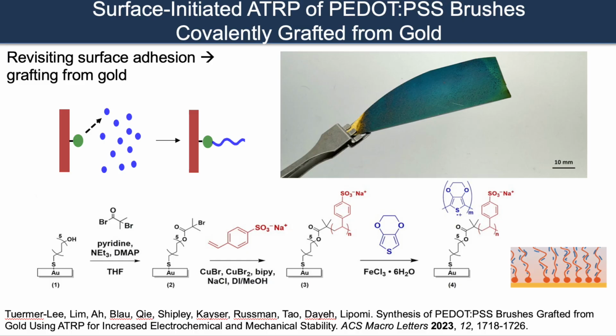We can increase the adhesion even more by actually chemically bonding these electrode materials directly to a metal, so that you can take what is ordinarily a decent or halfway decent neural electrode made out of a metal and kind of supercharge it by putting this conductive mixed electronic ionic soft hydrated material here to really give you a good electrochemical interface with the skin for good stimulation and neurological interfacing. And this technique is called atom transfer radical polymerization, where you bond the initiator for this polymer directly to this gold substrate, and then you use this bromine atom here to start growing your polymer chain.